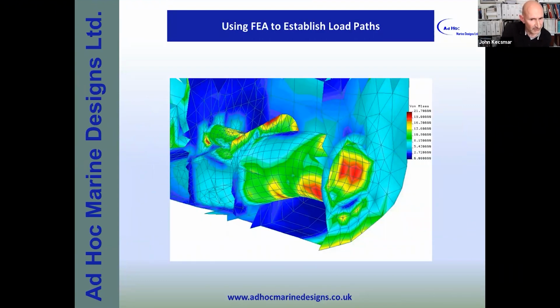And here is the resulting finite element analysis that I did of the water jet duct. And this is over 25 years ago. And I decided to just keep changing the structure until I actually got a value of around about 20 MPa. As you can see in the top right, actually got 21.7. So I thought, that's good enough for me, because it's not about the absolute value, it's about the trends. All we care about is the trends.